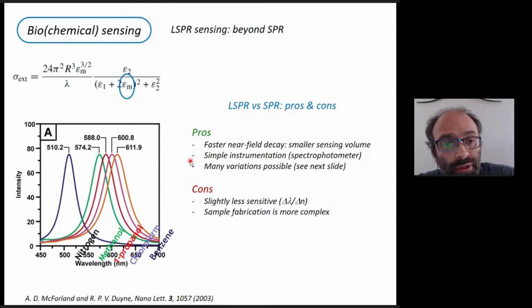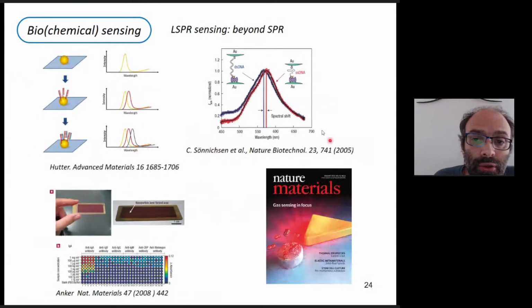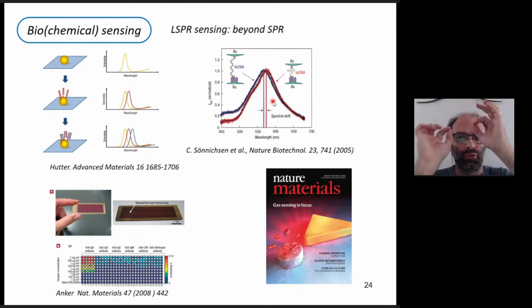And there are also more interesting advantages. For instance, you can do single particle experiments. I won't go into details, but this is a very, very nice experiment in which these scientists tracked the plasmon resonance position of one single couple of nanorods, okay, so 2 nanorods, and they changed the distance between the 2 nanorods by making a DNA strand shrink or expand, and they saw this change of plasmon resonance position with just one couple of nanoparticles.